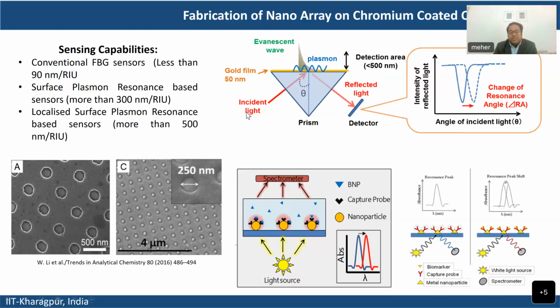But the problem with surface plasmon resonance based sensors is that you have to have such a geometry of the device. The incident light comes from one direction and goes out in another direction. In the case of optical fibers, the signal should come from here and should again go back to this side. So we cannot use this kind of geometry and technique for fibers especially. If you want to integrate some sensor on the tip of a fiber, the light should come in this direction and go back in the opposite direction without any deflection. So this was a challenge, but it is possible in the case of localized surface plasmon resonance-based sensors.